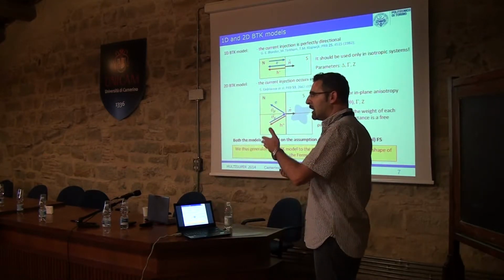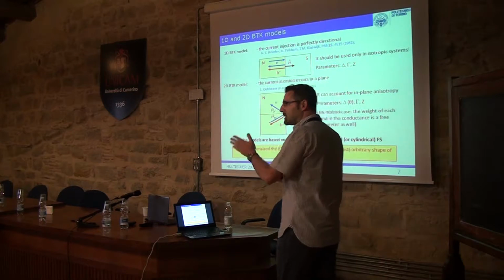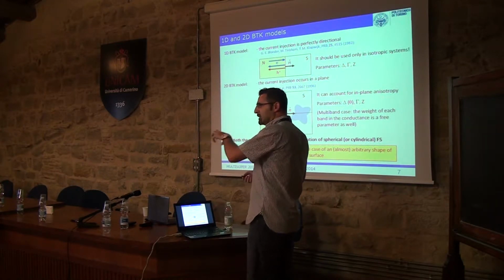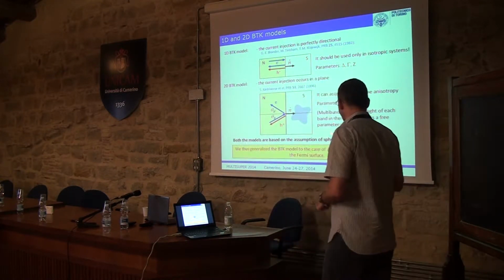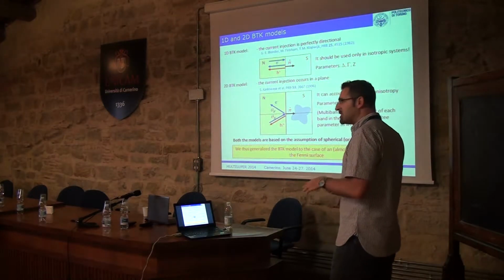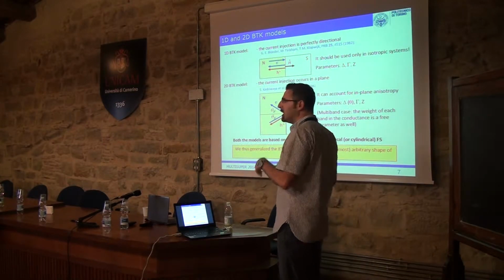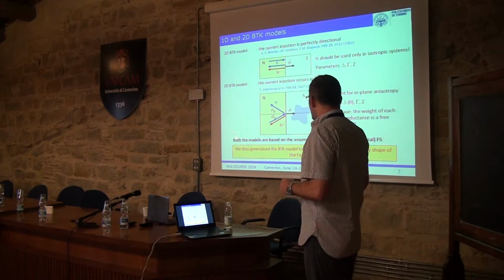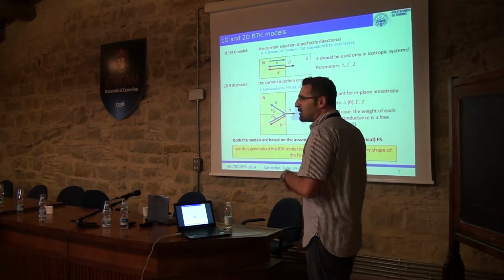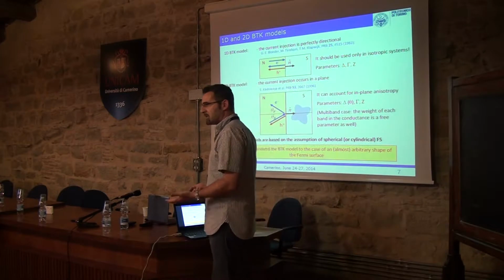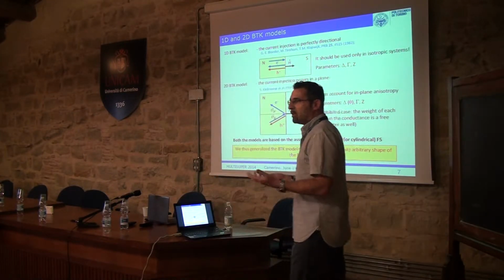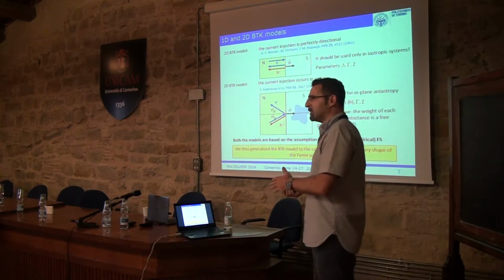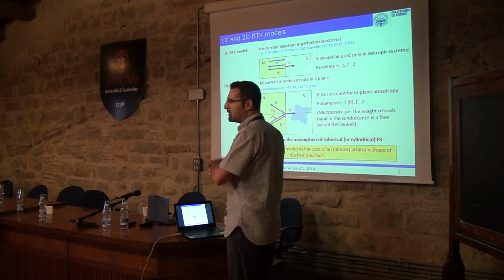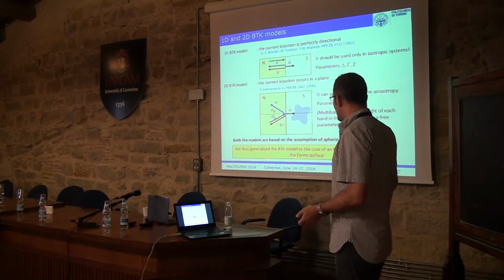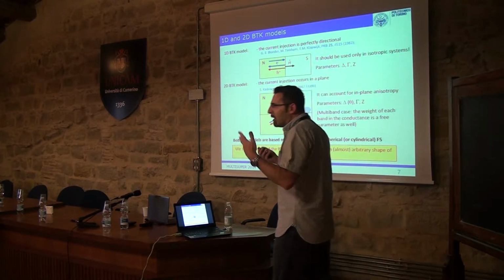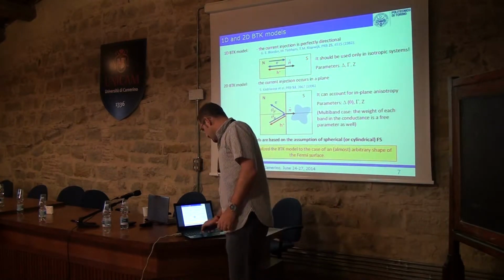So in that case, the contribution of different bands is simply summed with a weight which is specific for each band. But this is also only an approximation. This is not exactly true. Okay, this is true only in an approximate way. And the most important thing is that both the models are based on the assumption of spherical Fermi surfaces. And this is clearly not the case of iron-based compounds, where the Fermi surface is neither 2D nor completely 3D. And so we generalize the BTK model to the case of, let's say, an arbitrary shape of the Fermi surface.